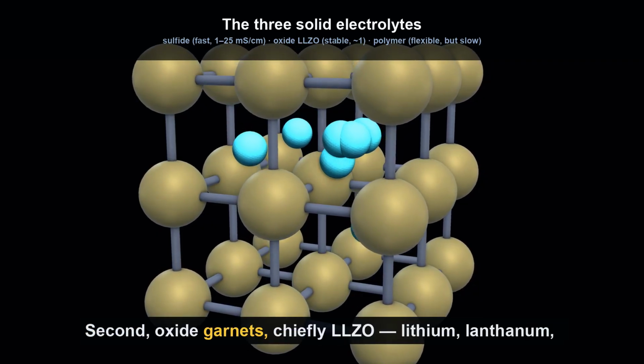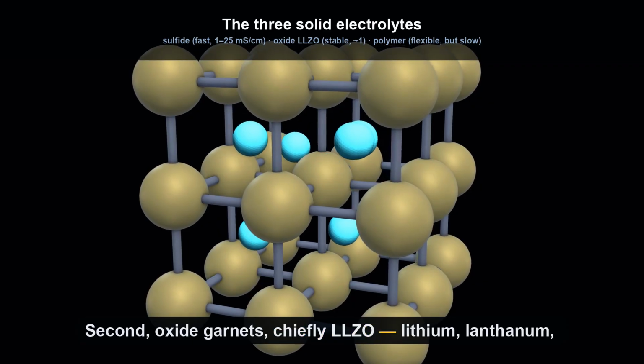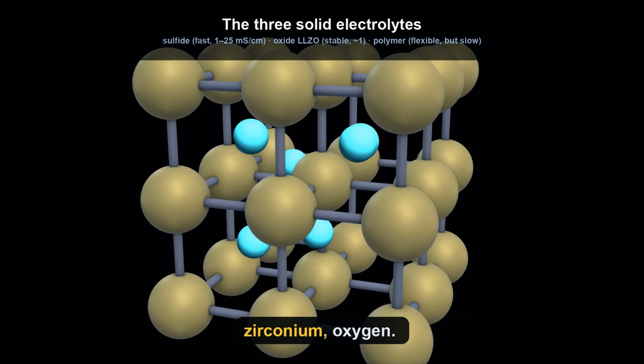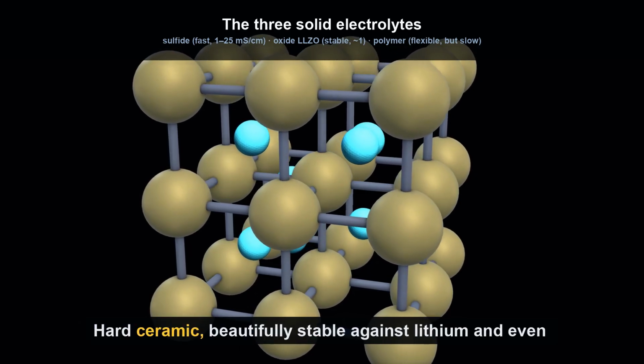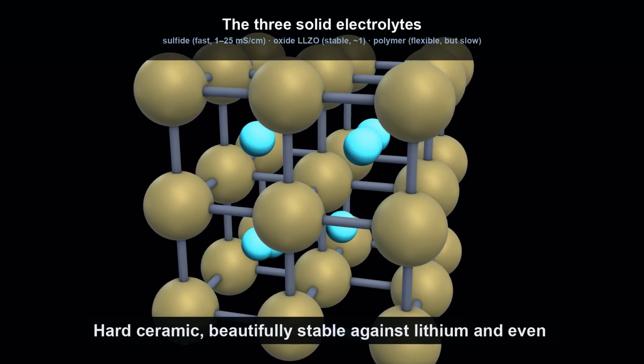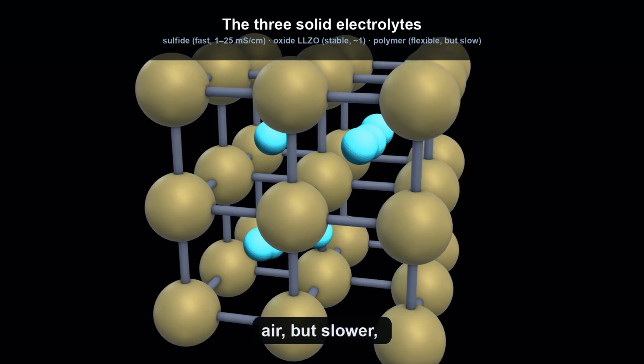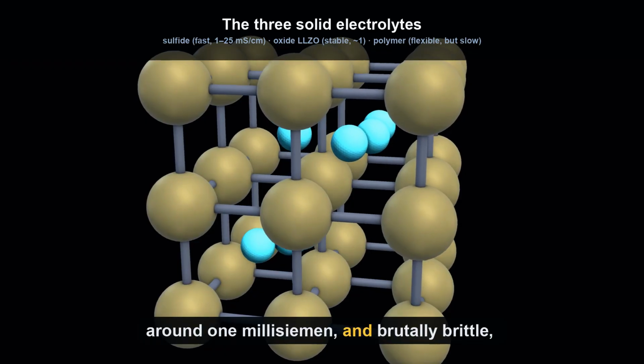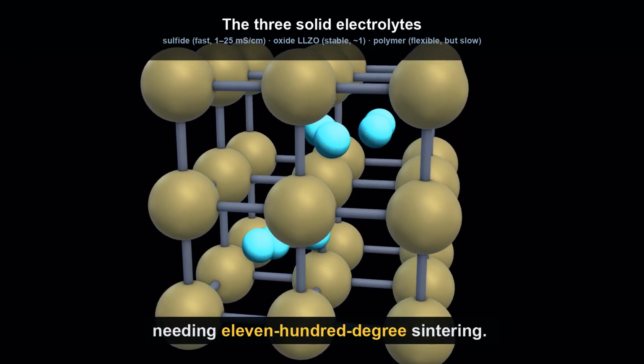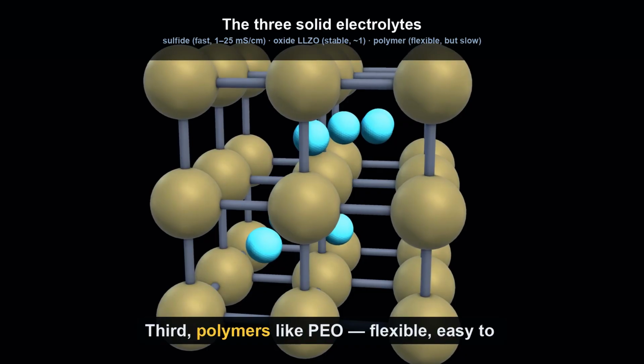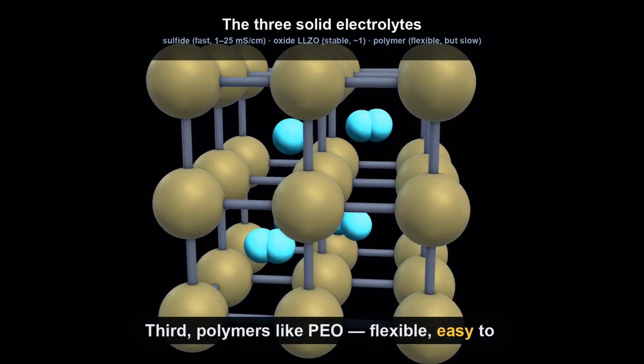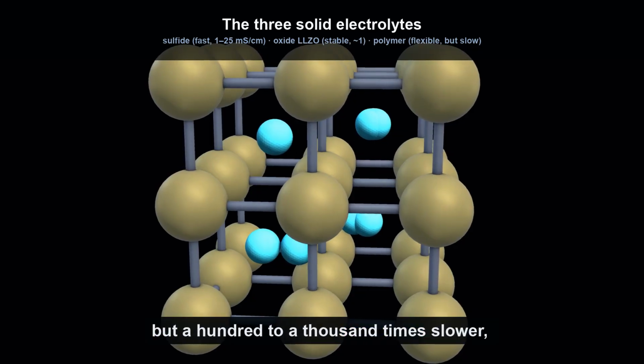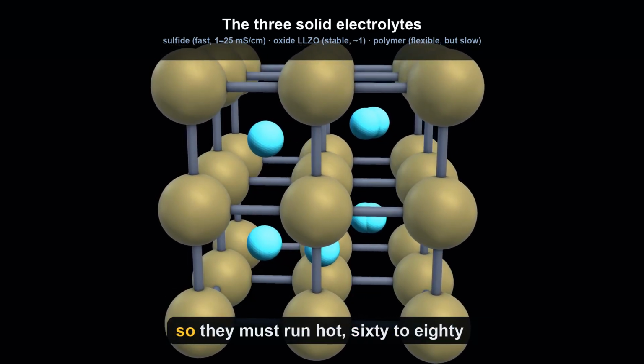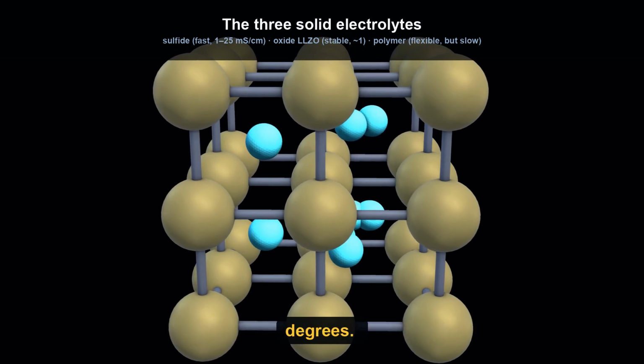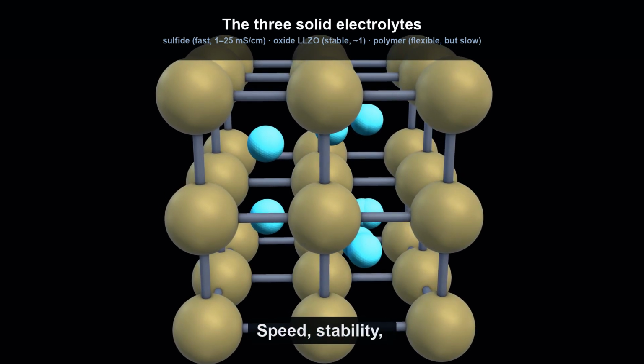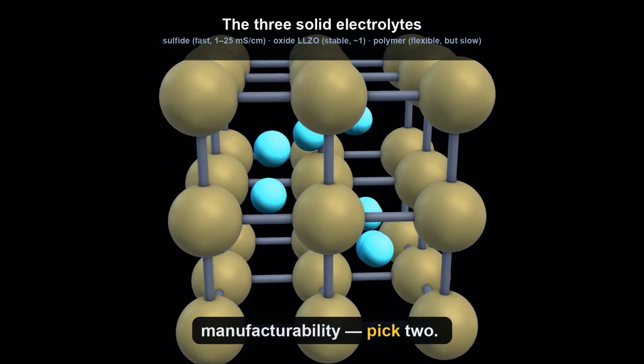Second, oxide garnets, chiefly LLZO: lithium, lanthanum, zirconium, oxygen. Hard ceramic, beautifully stable against lithium and even air, but slower, around 1 millisiemen, and brutally brittle, needing 1100 degree sintering. Third, polymers like PEO, flexible, easy to roll out in sheets, but 100 to 1,000 times slower, so they must run hot, 60 to 80 degrees. Speed, stability, manufacturability. Pick 2.